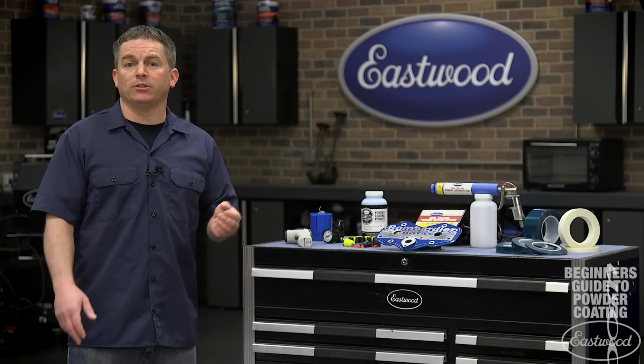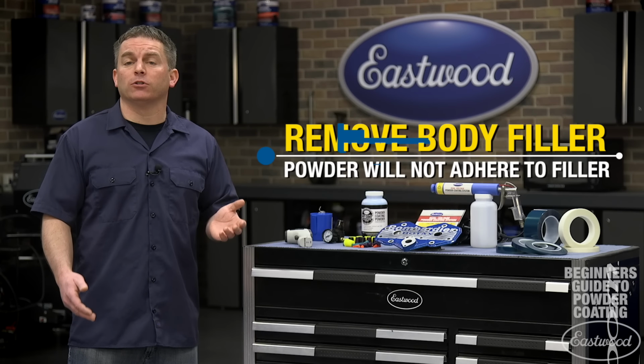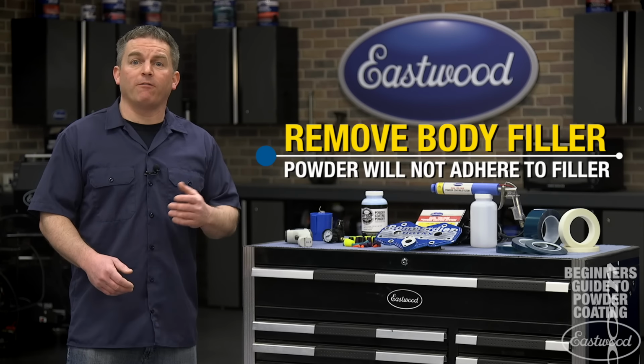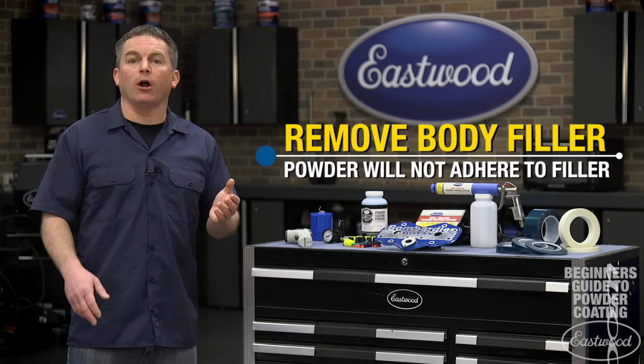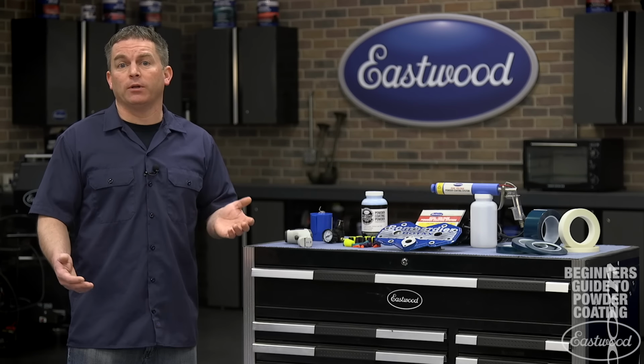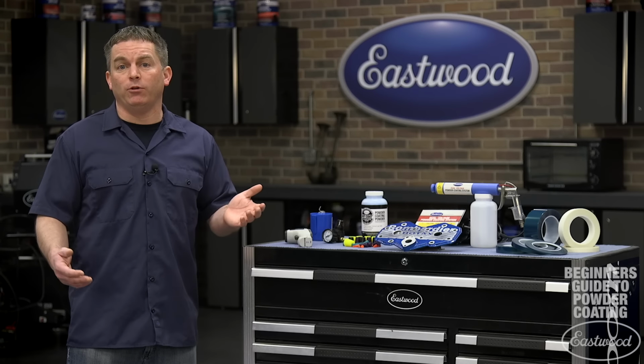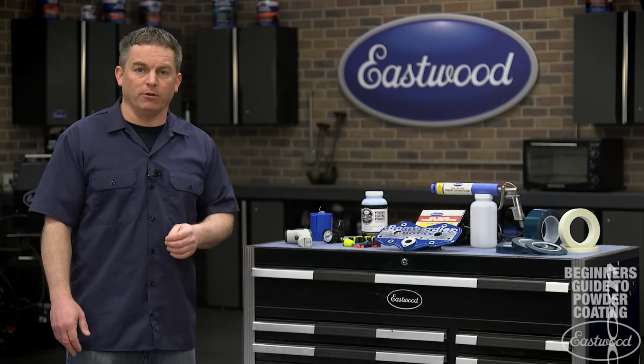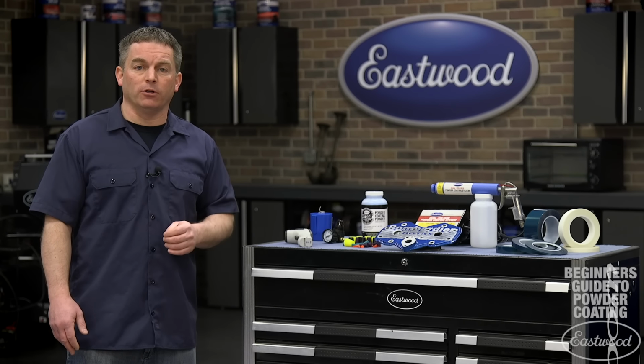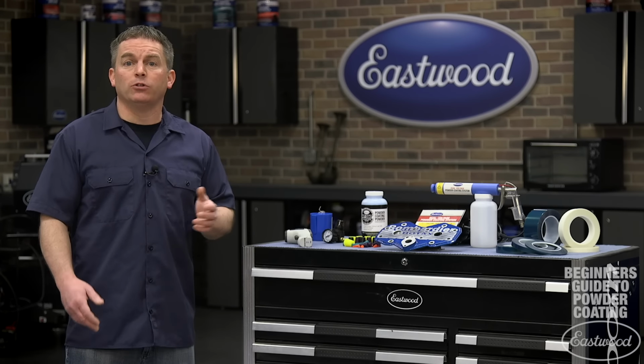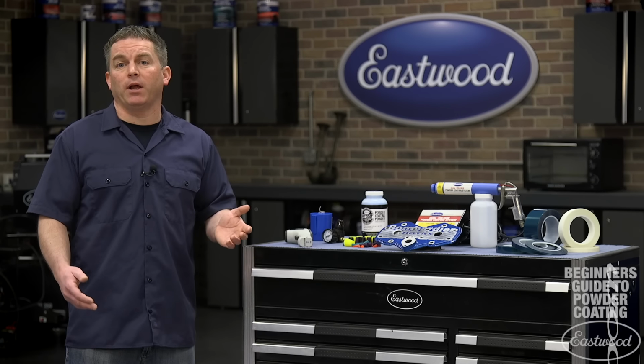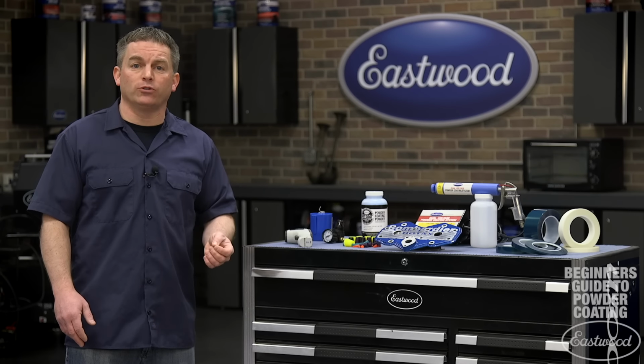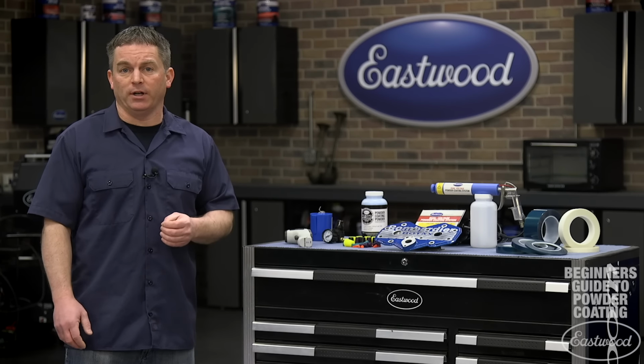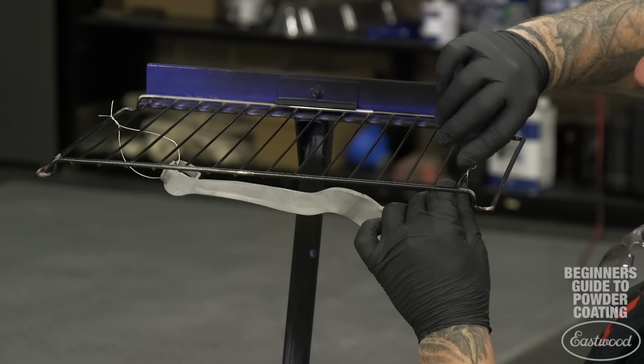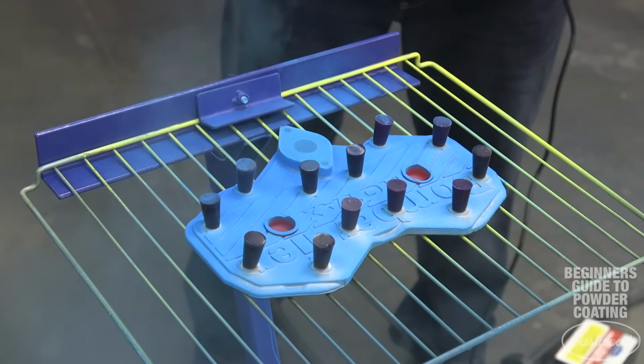And here are a few more things to look for. Many body fillers won't withstand the curing temperature, and fillers that will withstand the temperatures are not electrically conductive, so they will not accept the charged powder and will leave you with bare spots wherever there's body filler. So make sure all body filler is also removed. You should also avoid touching the parts with your bare hands because you will introduce oils to the part, which will also affect powder adhesion. Parts can be hung to be powder coated or placed directly on the rack.